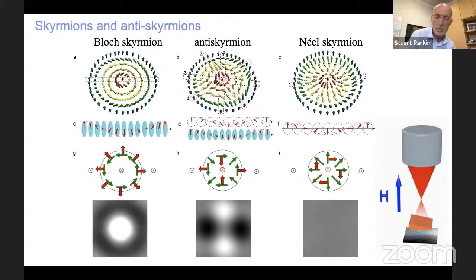So here we've carried out micromagnetic simulations of these structures and then carried out calculations of these forces on the electron beam and how the image would look in different focal planes or defocused planes. The Néel skyrmion, on the other hand, causes the electron beam to deflect around the circumference. So effectively, you don't see anything for normal incidence, shown on the right-hand side. But in the middle, the anti-skyrmion, you can see that we anticipate then seeing more complex forces on the electron beam, and you end up with this clover-like structure of two white regions of increased intensity and two black regions of decreased intensity, as you can see in this middle region.